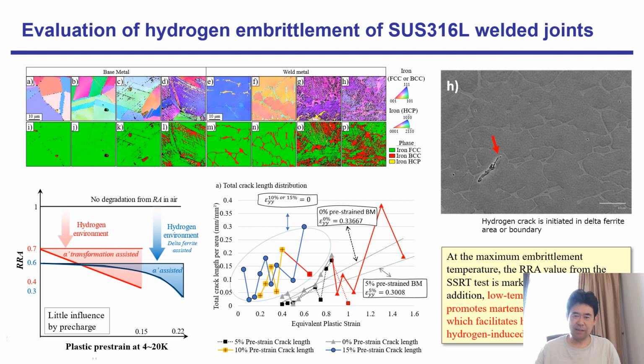Center graphic. This is a comparison of the starting point of surface crack formation versus specimen plastic strain. My student carefully observed this crack formation on the specimen surface under various plastic strain conditions. This is a very interesting test result. It tells us that specimens with 10% and more plastic pre-strain show a surface crack in the early stage, so 10% or 15%. On the other hand, virgin steel or 5% pre-strain steel shows no crack in the early stage. And from 40%, the lattice crack, lateral crack, started to initiate.